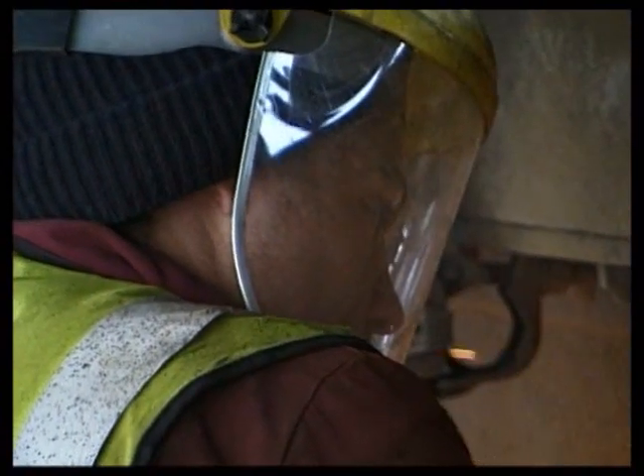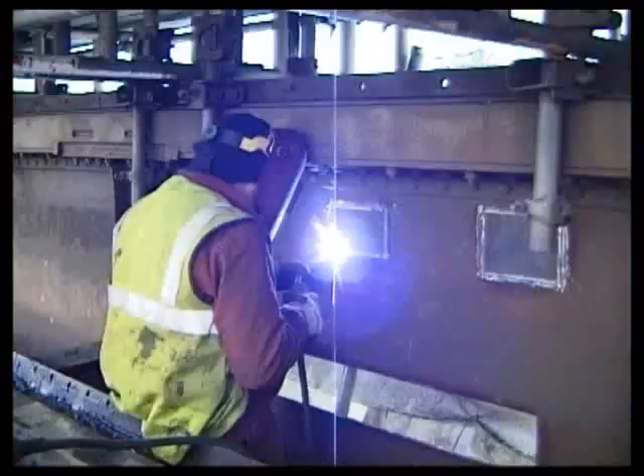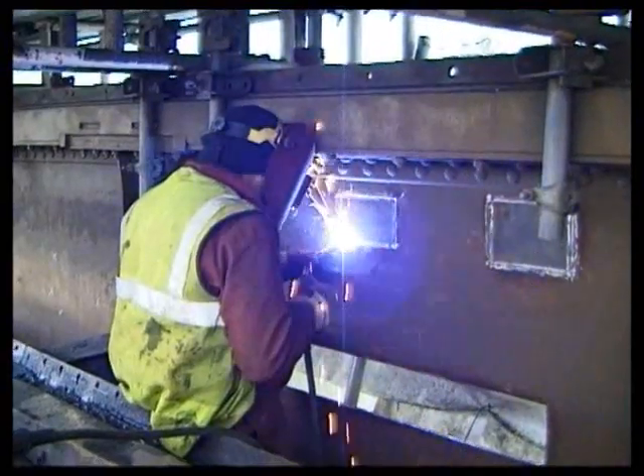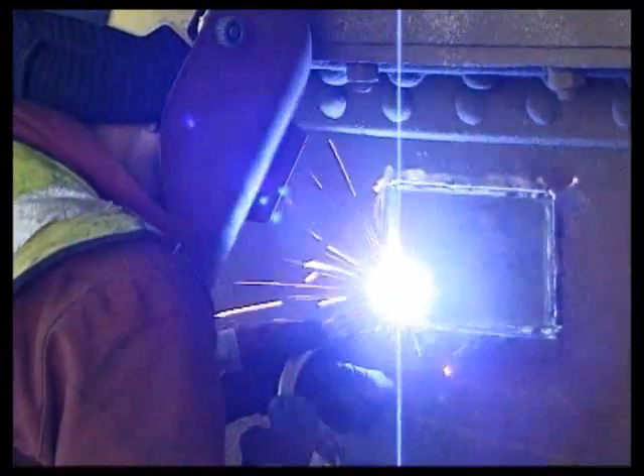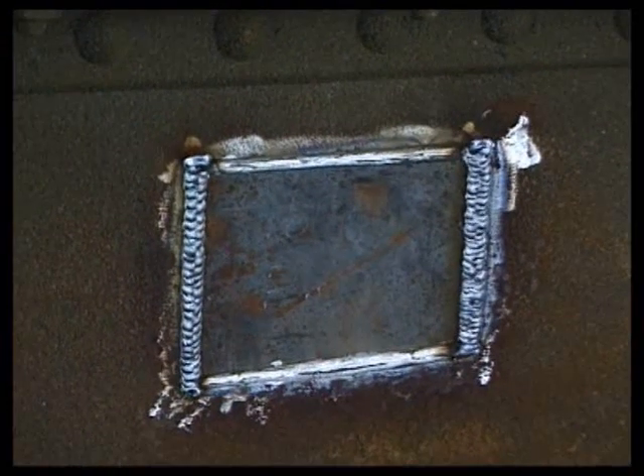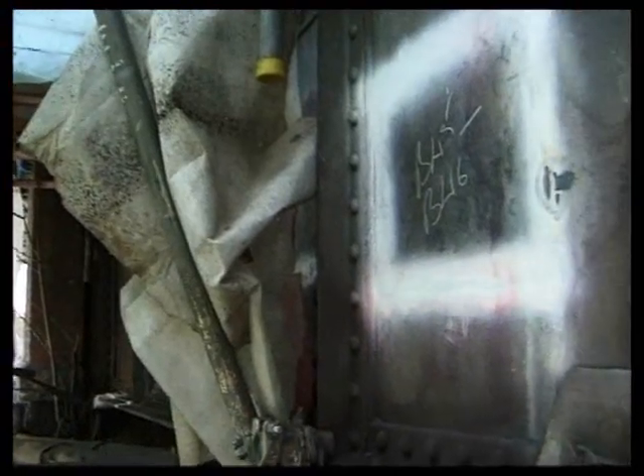The plates of the main span were just 6 mm thick, so a full depth weld from both sides was essential. Wrought iron is fibrous and contains small natural faults. The contraction of the hot weld often pulls the fibres apart, so it's important to test structural repairs for cracks.